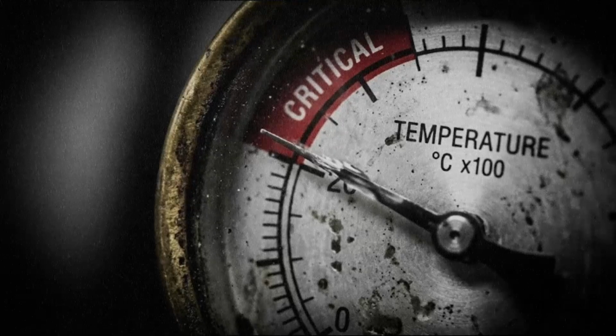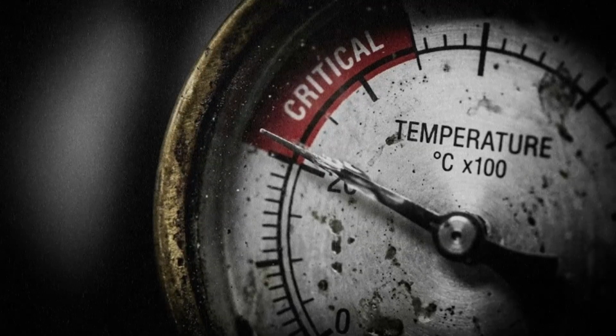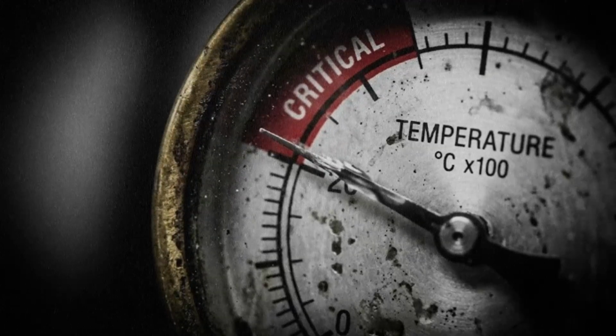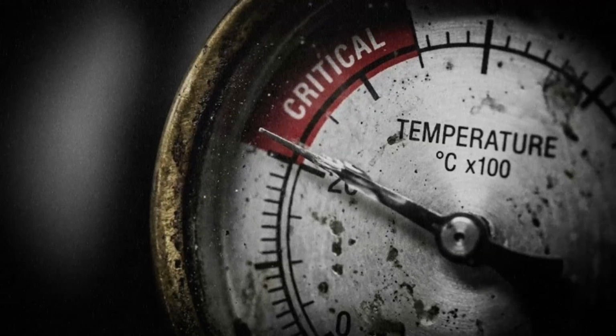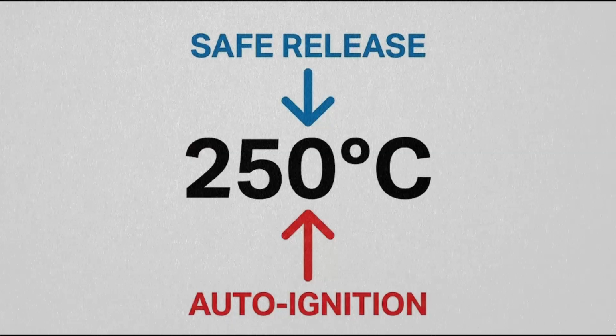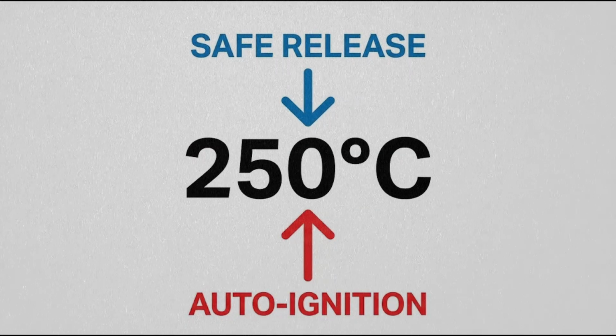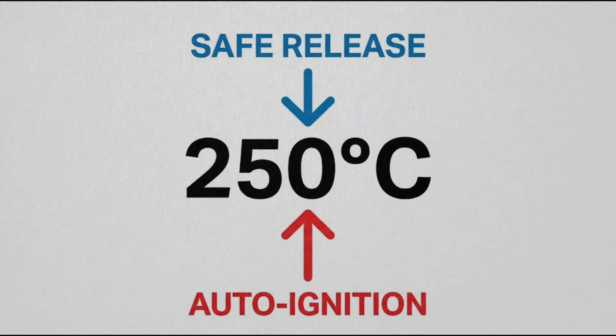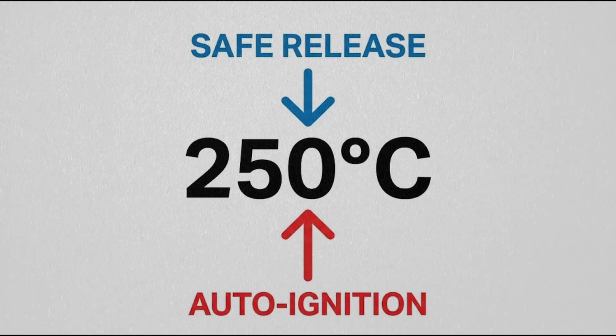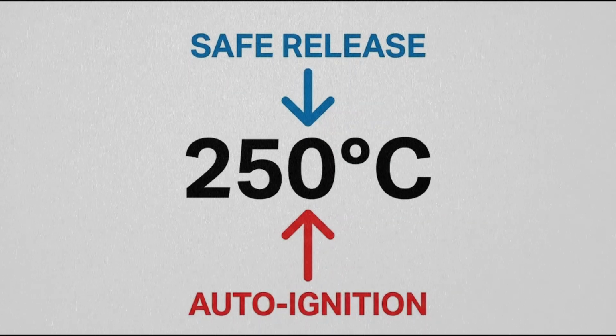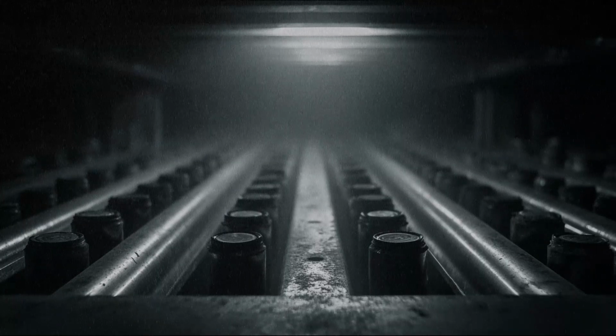250 degrees Celsius. That was also the target temperature for the annealing procedure, the very process designed to keep the reactor safe. The temperature needed to release Wigner energy safely? 250 degrees. The temperature at which the fuel catches fire? 250 degrees. The margin between safety and catastrophe was 0. And the uranium was not alone.